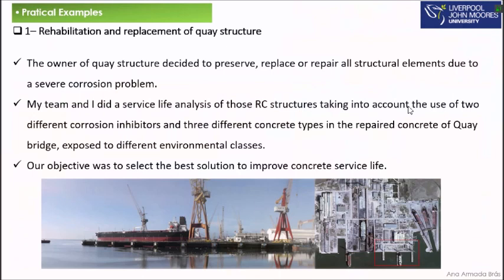So we tested 3 different concrete compositions with 2 corrosion inhibitors to check the service life, and then we could select the best option to repair the structure. So our objective was to select the best solution to improve the concrete service life. So performance-based design was used in this situation.